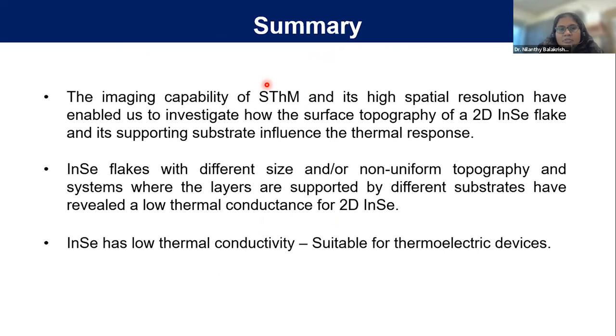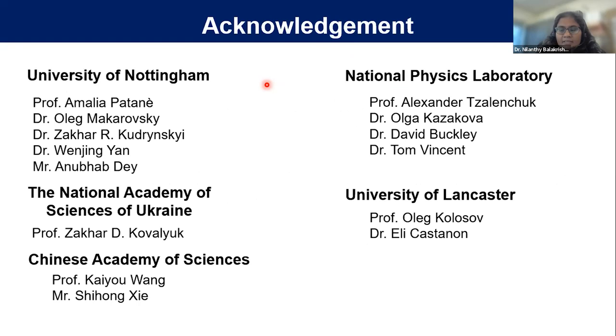In summary, the imaging capability and high spatial resolution of scanning thermal microscopy have enabled us to investigate how the surface topography of 2D indium selenide flakes and their supporting substrate influence the thermal response. Indium selenide flakes with different sizes and non-uniform topography consistently show lower thermal conductivity. Importantly, indium selenide has both low thermal conductivity and high electron mobility, making it really suitable for thermoelectric device applications. Thank you to our collaborators.